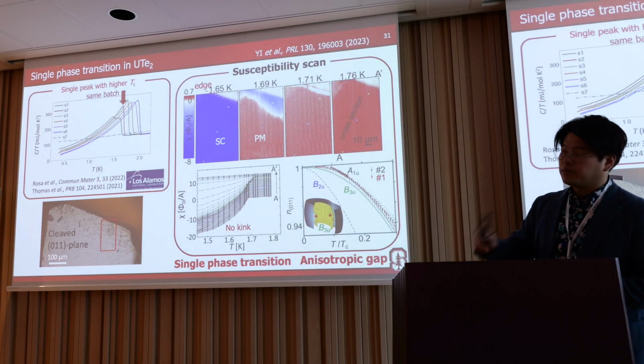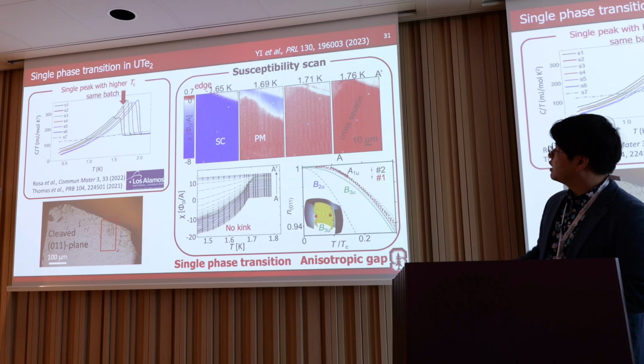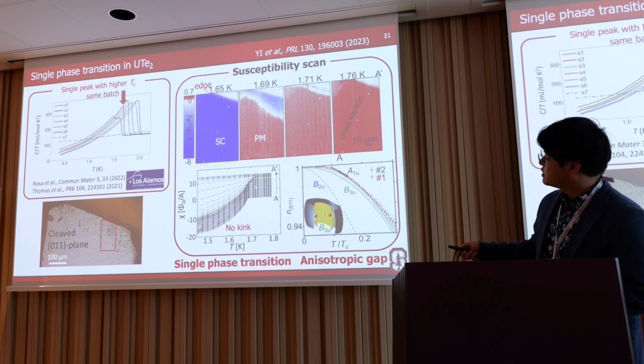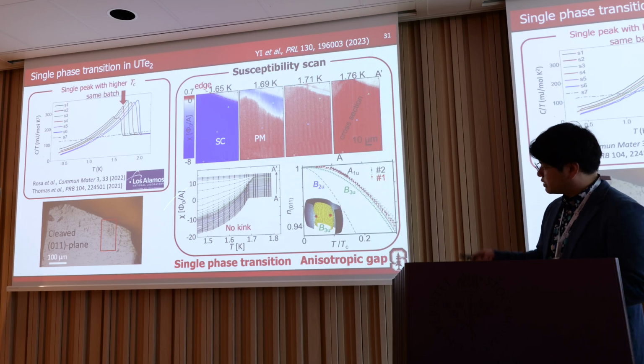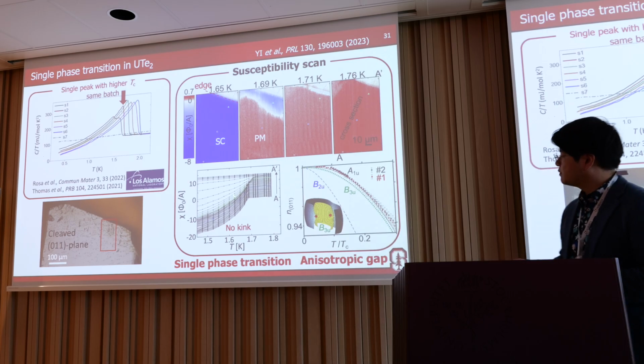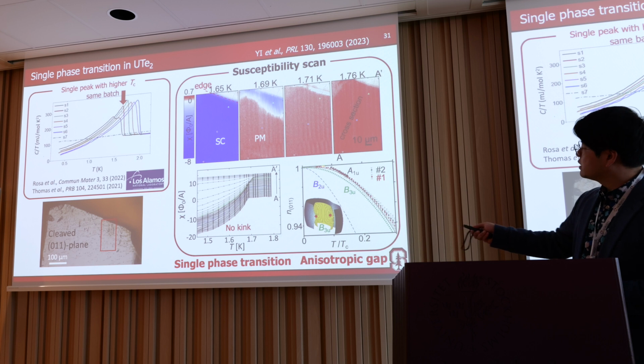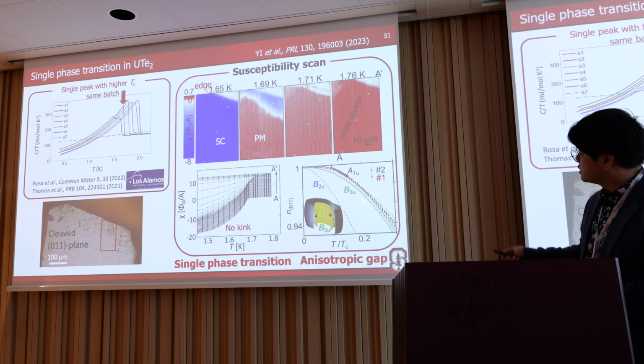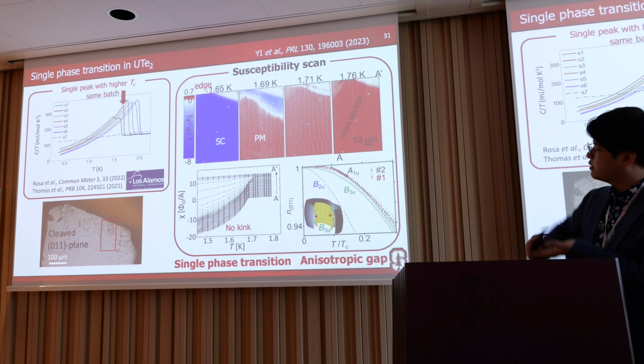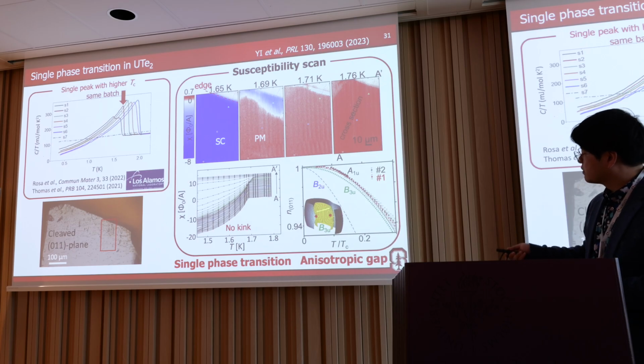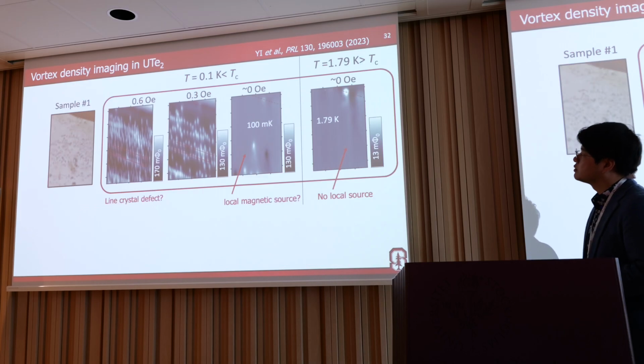Then the susceptibility measurement near TC shows a very clean single phase transition, and there's no kink below TC. It's obvious this is a single phase transition. We also measured the superfluid density at low temperature. This is consistent with a point node or very small local minima along these directions. It's consistent with an anisotropic gap in the sample.